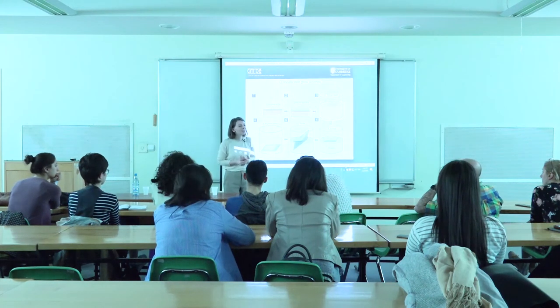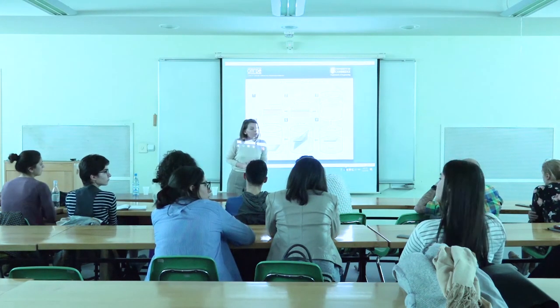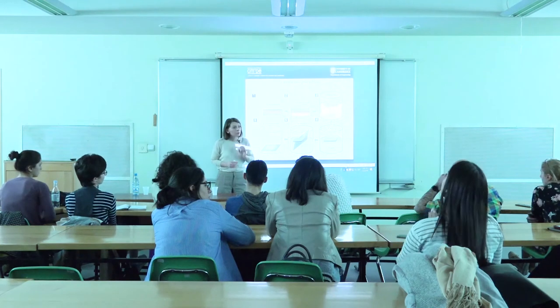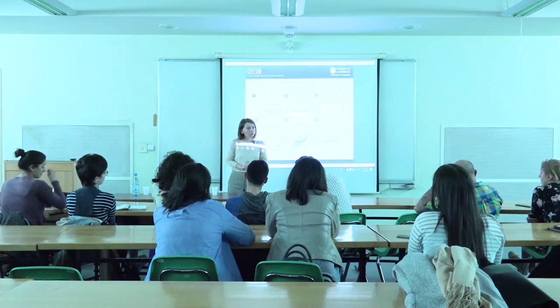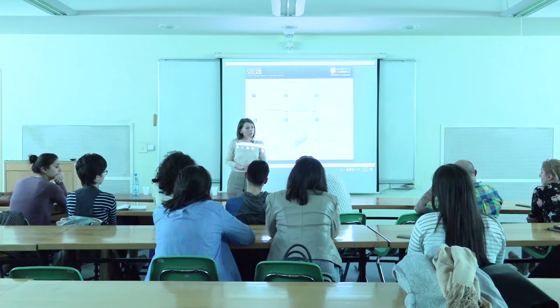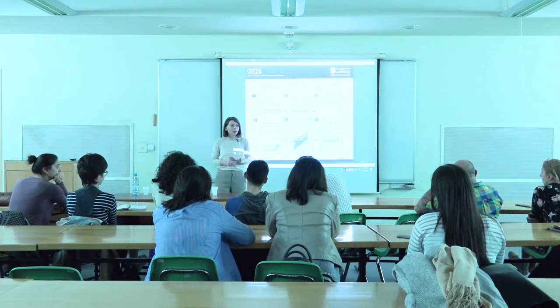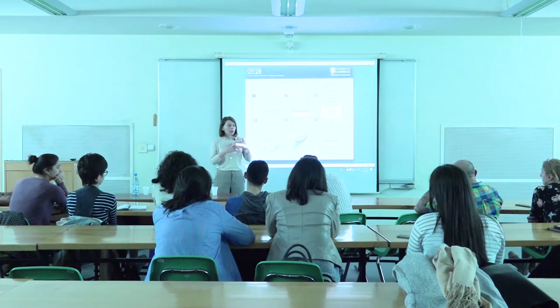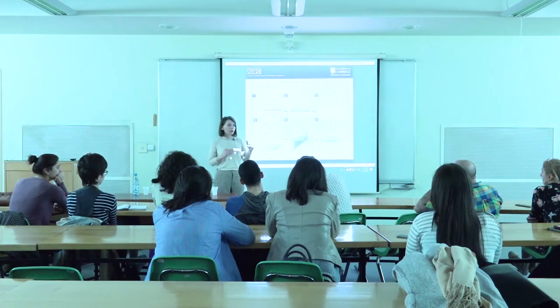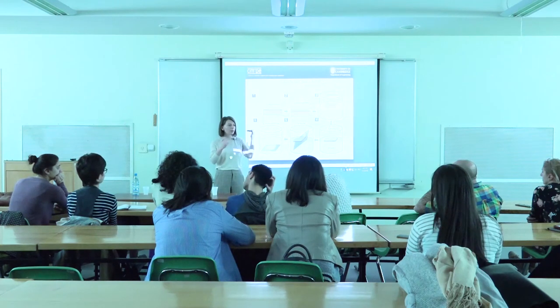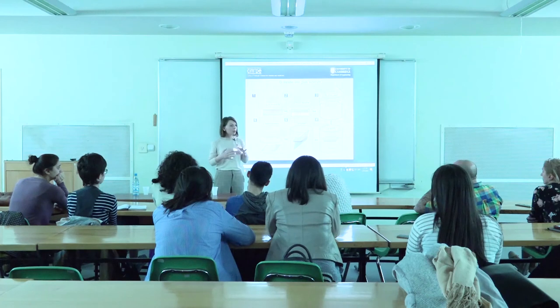Yes, please. You mentioned the optical properties of graphene. Which outstanding properties are really interesting? So the first one, because it's one atomic layer, it has only 3% absorption. By adding up layers, we end up... and when it is one atomic layer, the band structure is such that the valence band and conduction band are almost overlapping. So it's kind of a semi-metal.